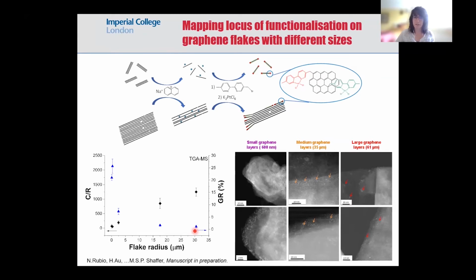From scanning transmission electron microscopy, we look at three different graphene sizes: small graphenes around 600 nanometers, medium-sized graphenes 35 micrometers, and much larger graphenes around 60 micrometers. So we were able to see these platinum atoms from the different samples. For the smaller graphenes, we can see how the platinum atoms are uniformly, homogeneously distributed across the graphene layers.